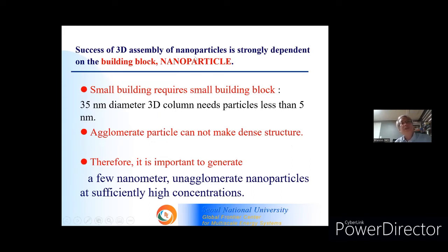Success of 3D assembly of nanoparticles is strongly dependent on the building block nanoparticle. It is natural and obvious that small building requires a small building block. For example, a 35 nanometer diameter 3D column needs particles less than 5 nanometers. We cannot make a 35 nanometer 3D column with a 10 nanometer or 20 nanometer particle—too big.